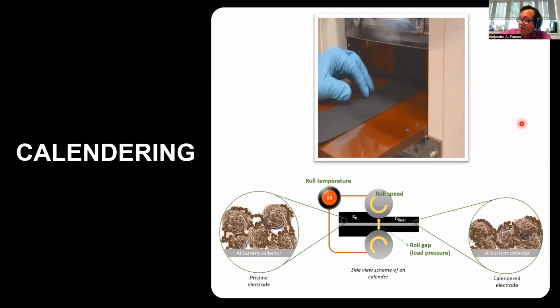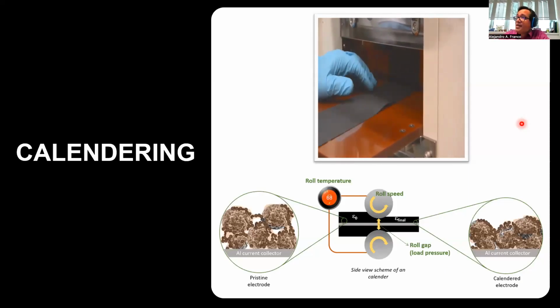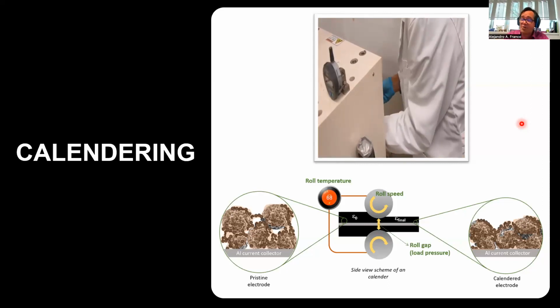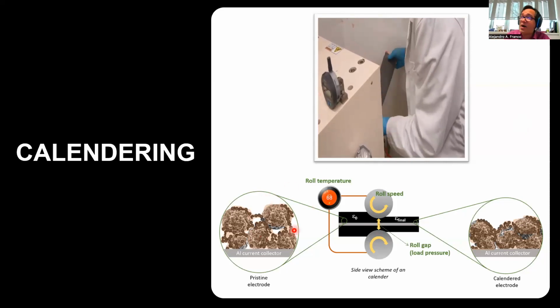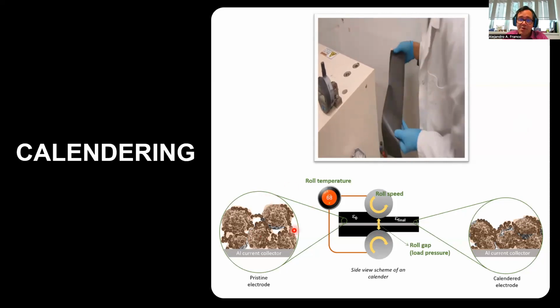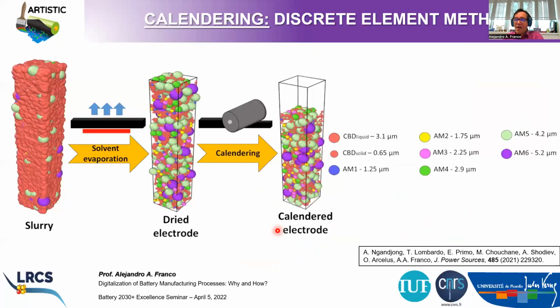The next step in the digitalization of battery manufacturing is the calendering. The calendering is a very important step because you need to press the electrode in order to improve the electronic contact between the particles, right? But at the same time, you need to avoid pressing too much because you will otherwise collapse the pores, and then it will be very difficult for the liquid electrolyte to go in, right? And then you will have problems with wettability of your electrodes. Therefore, it's very important to optimize this process, right? And to perform calendering, but not too much, right? And this is why some modeling also can be very useful in this regard.